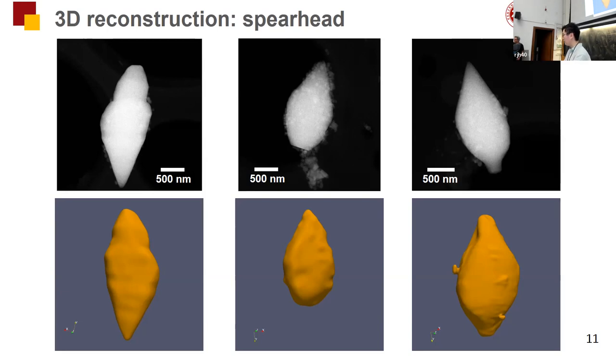There's also some evidence that the magnetosomes themselves may effectively be a biobattery, and that the magnetic fields they generate may contribute to the physical chemical pathways controlling migration or diffusion of ions within the bacteria itself. How robust that is is still debated, but these unusual geometries will create unusual stray fields, and that might tie into the biology. When these grow, you've got a balance of the growth of the crystal and biological constraint, because they grow within a membrane. So they are physically bounded, and the shape and flexibility of that membrane will impose a control on the shape as well.